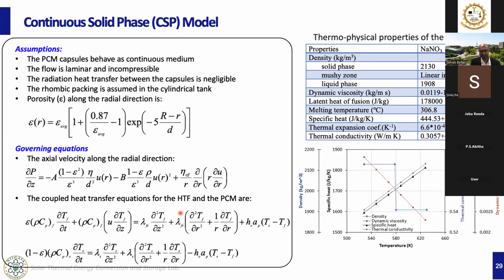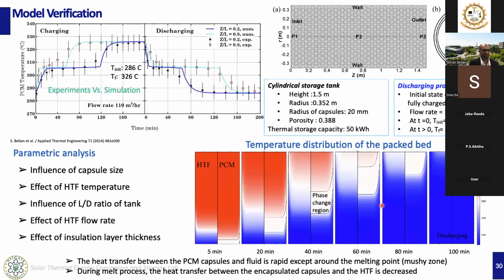And these are the thermophysical properties of the phase change materials used in the model. To verify the model, we conducted charging and discharging experiments and simulations for the operating conditions shown here. For example, the initial bed temperature would be 286 degrees Celsius, and you can see the fluid temperature and the flow rate here. For these operating conditions, we did the charging experiments and similarly discharging experiments, and thermocouples installed at different locations inside the tank measured the temperature as a function of time. For the same conditions, we did the simulation as well. As you can see, a good agreement has been found between the simulation and experimental results.